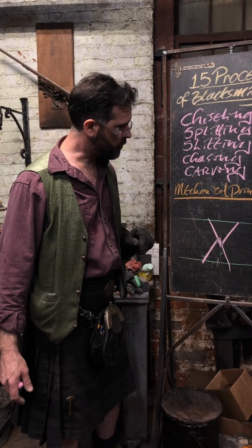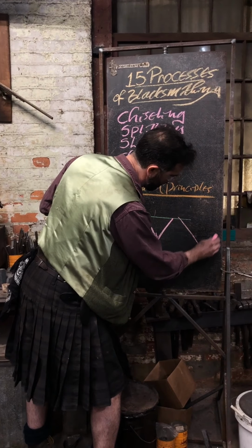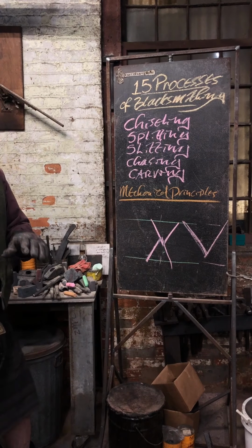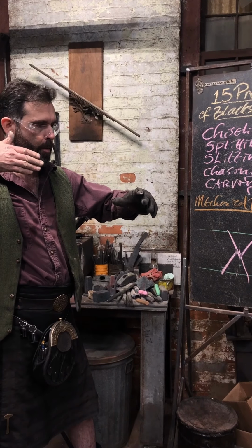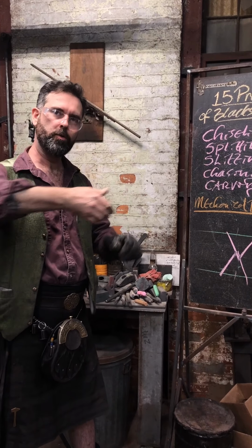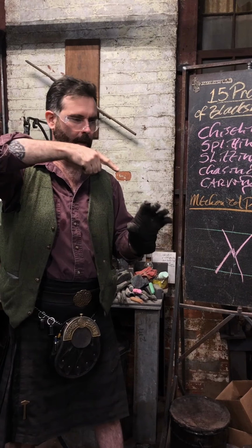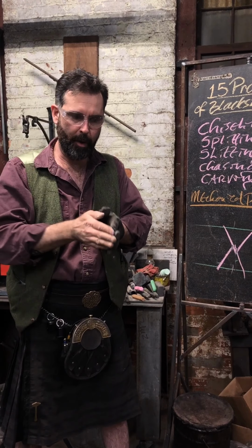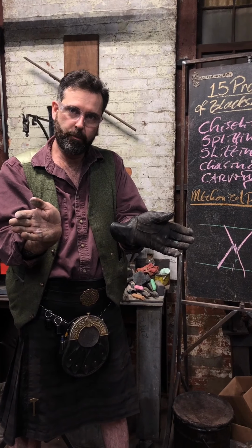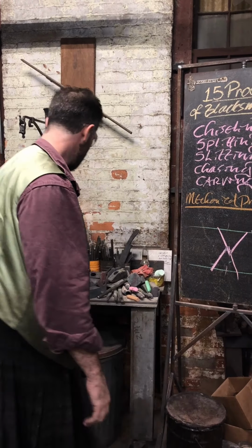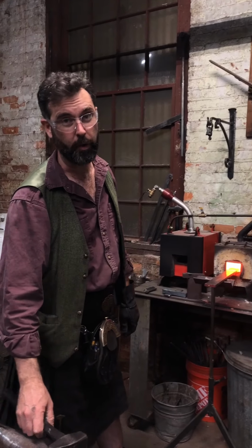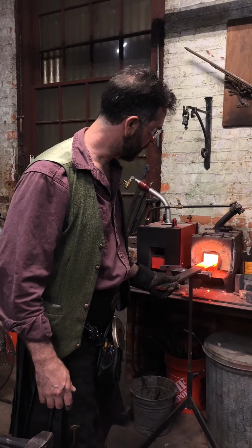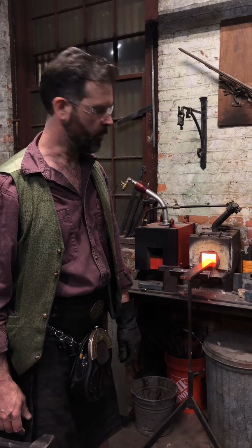So in order to solve that problem, another way to do it is come down 90% from one side and then approach it from behind but at an angle. So you're coming in this way at it, so probably at like 22 degrees. And then you're not so much cutting down from above, but cutting from the end and splitting it in that manner. You'll find what works for you based upon your requirements, your mechanics, but these are just to give you some good baseline profiles to start with.